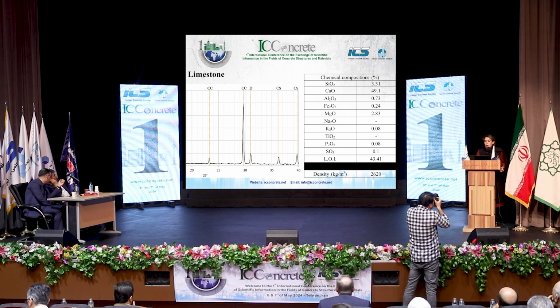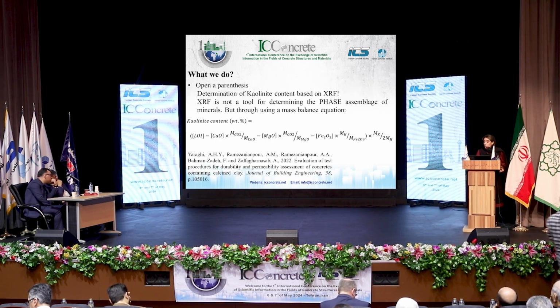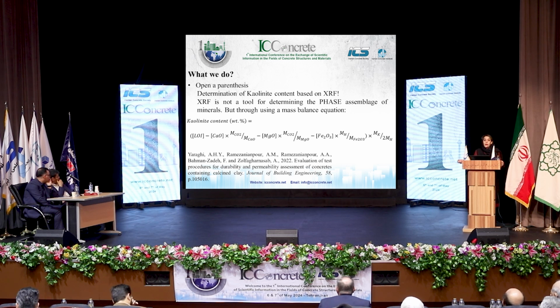As I said, we have good resources of limestone. Let's open a parenthesis. After our study in the field of LC3, we suggest an estimated equation for measuring the kaolin content in raw clays. It does not need a very complicated test like TG to reach the kaolin content. Just by XRF analysis, which is used for measuring the chemical composition, which cannot demonstrate the mineralogy, we can measure the kaolin content. In this paper, you can find this equation.